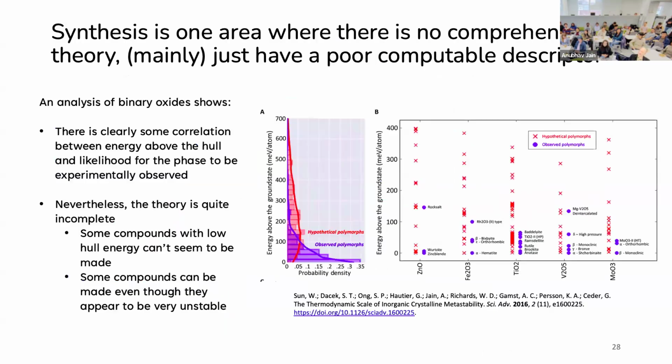Yeah, so what's typically done is you can add temperature dependence for vibrational entropy properties. Basically the temperature dependence of the thermodynamic stability comes from the entropic properties of your materials. There are different components of your material's entropy: vibrational, electronic, configurational, etc. People have done this for the vibrational entropy, which is probably the most important one to do as you move to finite temperature. So that lets you look at these thermodynamic stabilities at finite temperature, and not just at 0 Kelvin.